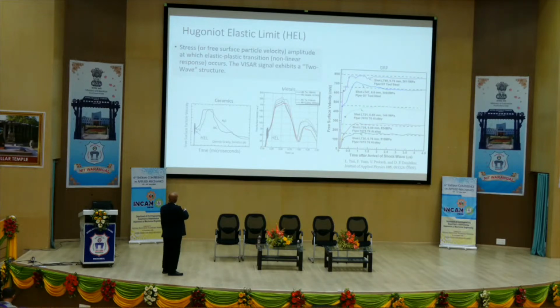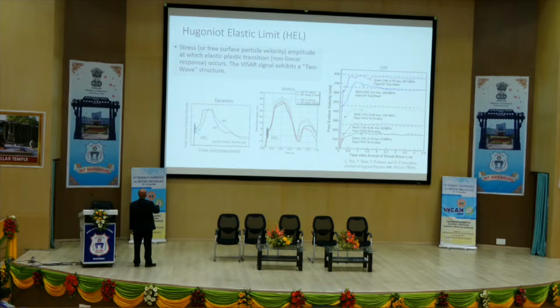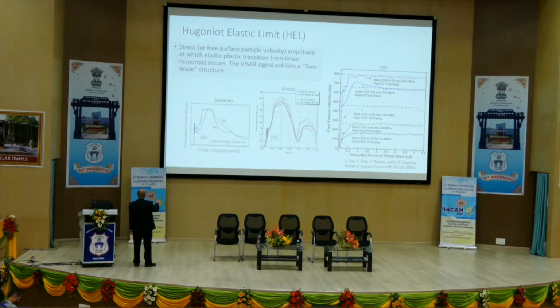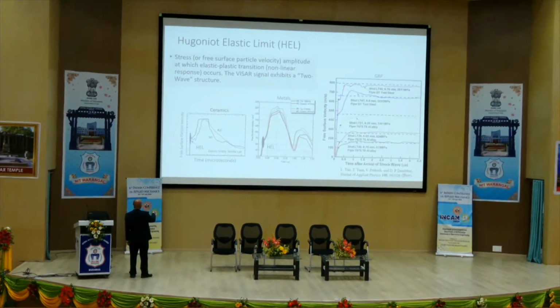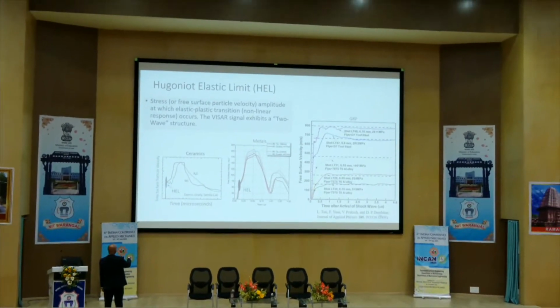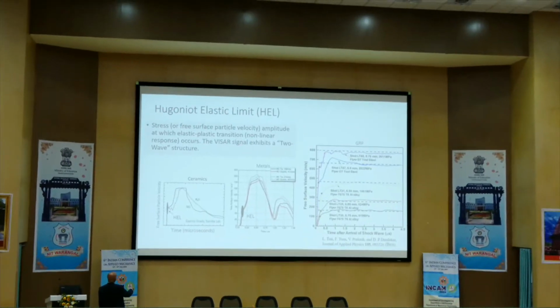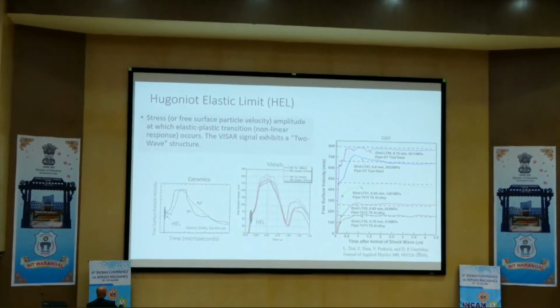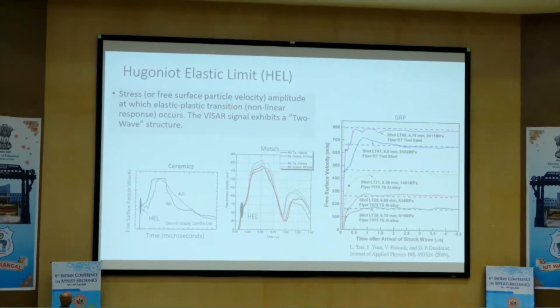One for ceramics. So if the target plate is ceramic, you get something like this. Elastic, some transition to elastic plastic or elastic inelastic, and then you see the wave dispersion, and then it reaches the shock stress that is controlled by equation of state, and then it releases. All right. This is silicon carbide, that is boron carbide.